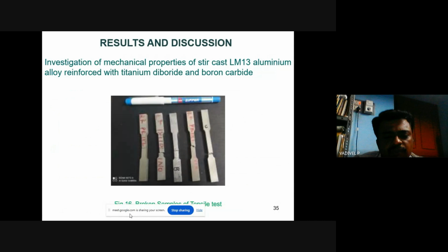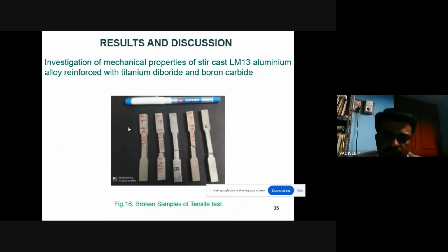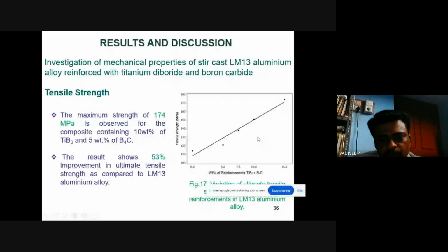And the next one is the tensile test. These are the tensile specimens prepared for the tensile test. While plotting the tensile strength, we have reinforcement on the X-axis and the tensile strength in megapascal. The test results show that the maximum strength of 174 megapascal is observed for composites containing 10 weight percentage of titanium diboride and 5 percentage of boron carbide.